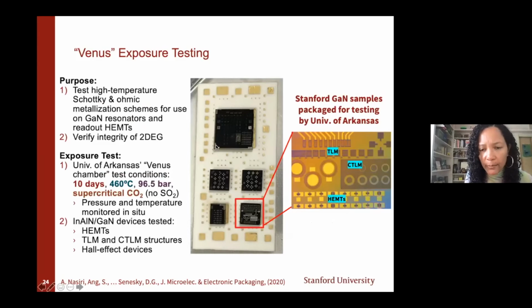Once we have fabricated our devices, it's important to also look at the packaging. This is another element of the technology that's really, really important. We've been working closely with researchers at University of Arkansas to study how we can take our gallium nitride chips and bond them to boards, because right now we were just looking at individual elements, but one day we might want to have more complex circuits. So we need to do die attach, we need to do wire bonding. These are all important things for micro and nano electronics. What we do is leverage low temperature co-fired ceramic and also special high temperature pastes in order to create these die attach with electrical interconnect. And then we also do wire bonding as well, typically gold wire bonding.